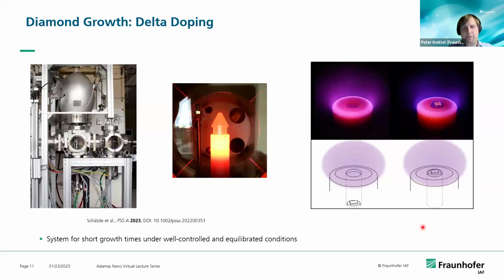Then we have one special type of reactor, or actually nowadays two, that allow us also to decouple the growth preparation steps in the machine from the substrate. So in lots of other, also commercially available machines, you always have the diamond in touch with your plasma from the point where you actually ignite the plasma till you end your process. Here we can equilibrate conditions. We can remove the diamond from the active plasma, stop the growth in such a way, and this gives us the chance to actually grow for very short periods of time. And we specifically made these to produce delta-doped layers that you will see later on.